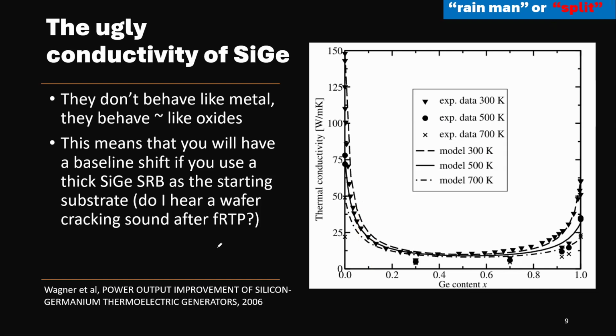So what is the complication of that then? Well, one of the famous complications is that if you use SiGe as the stress relief buffer, SRB, that layer is thick, microns, right? You need some microns in order to get rid of the dislocations when you grow from the silicon to SiGe as a buffer. This has been a very famous study using SiGe, right? Samsung and IBM tried to do that and eventually failed, but it has been tried for the 7 nanometer. And that is a lot of good benefit. It will stress PFET and NFET at the same time. That's the beauty of it.